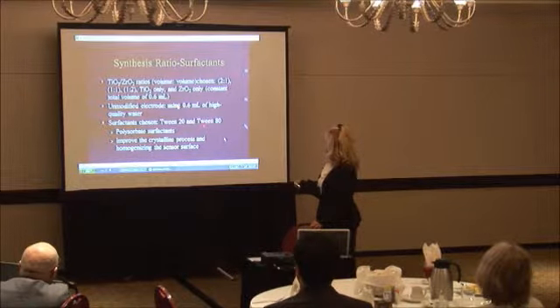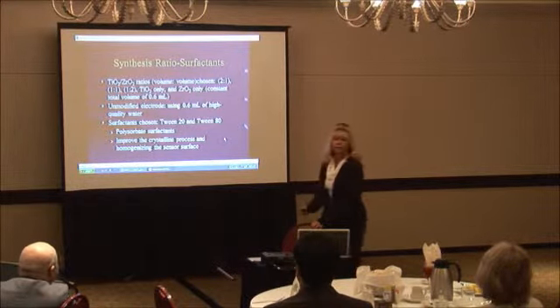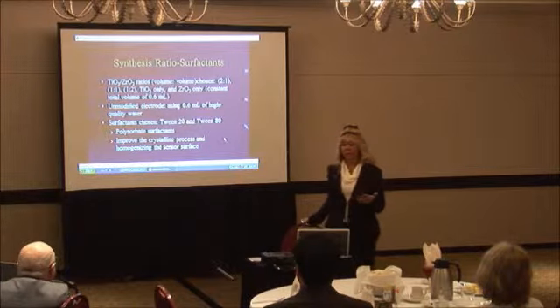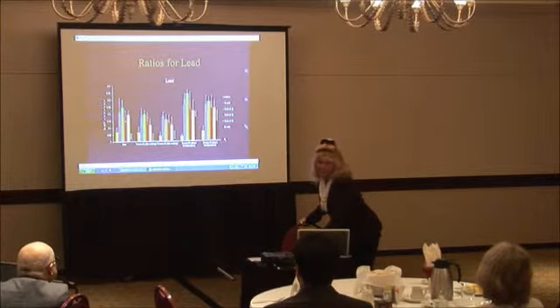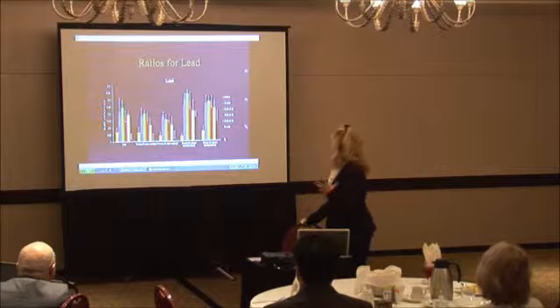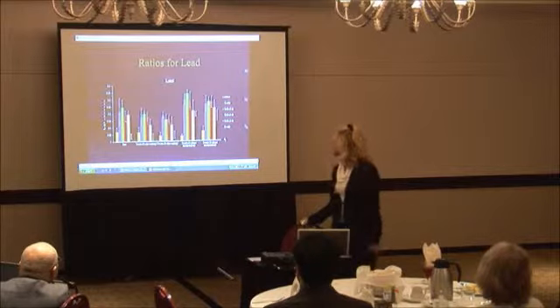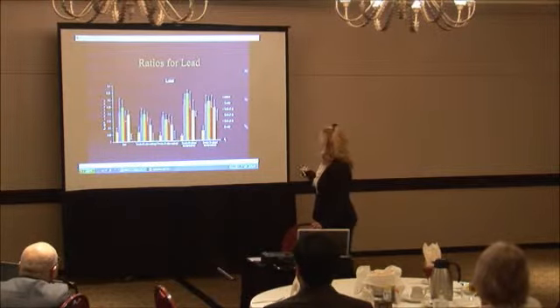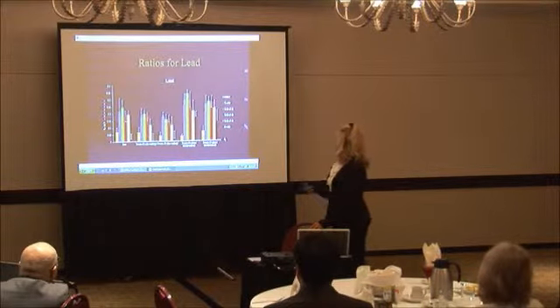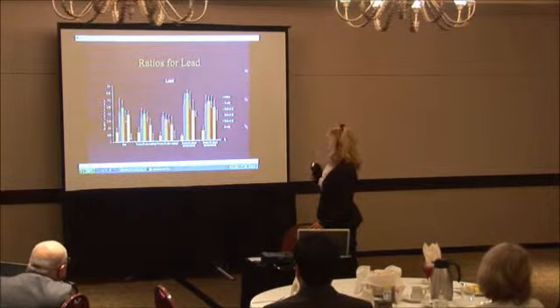The Tween 20 and the Tween 80 was what they were looking at, how they optimized choosing the right surfactant in the process. And so there's ratios to look at what ratio worked best: titanium, zirconium, or zirconium only for the sol-gel synthesis. And the biggest thing they find is, obviously, it's a titanium-zirconium ratio that happens for the detection of lead, which is really good for the students to learn about, again, graphing.